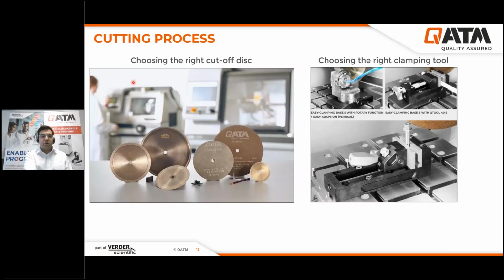Here are some hints for the cutting process. On the left-hand side, you can see that choosing the right cutoff disc is very important. We have different cutoff discs for different materials, for example aluminum oxide, silicon carbide, as well as diamond and CBN cutoff discs. And also choosing the right clamping tool. For example, here you can see the Q-Tool 40S is a manual clamping tool that you can fix your sample with manual force, and it is very good for porous materials that are not very stable. To cut porous material, it is always a good idea to mount the sample before cutting.